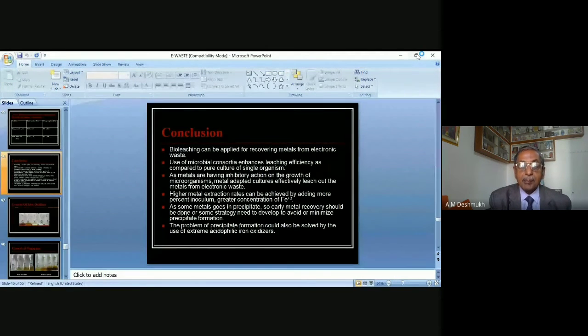Higher metal extraction rates can be achieved by adding a higher percentage of inoculum. If the inoculum percentage is increased, we obtain better results. If the concentration of Fe3+ is increased, we obtain better results. As soon as the metal goes to precipitate, early metal recovery should be done, or some strategy needs to be developed to avoid or minimize precipitate formation. That's why we used citric acid, which avoids the precipitation and causes more and more solubilization.